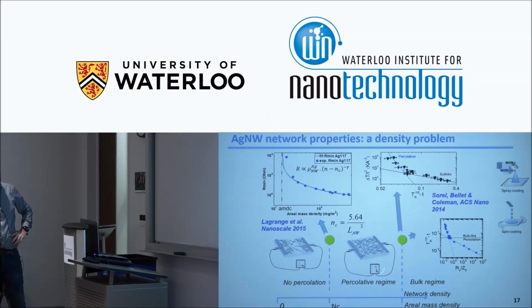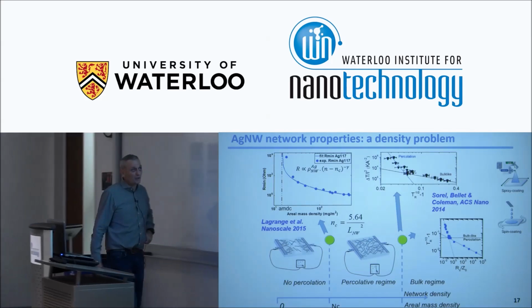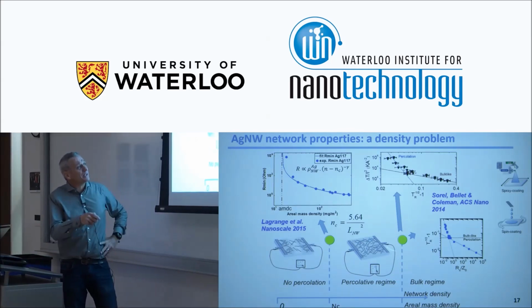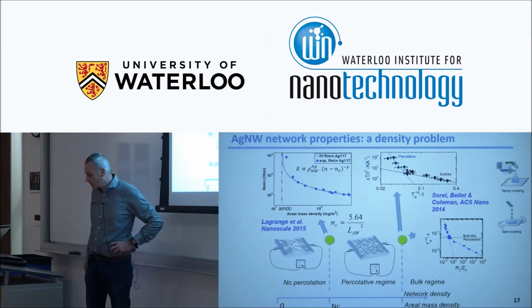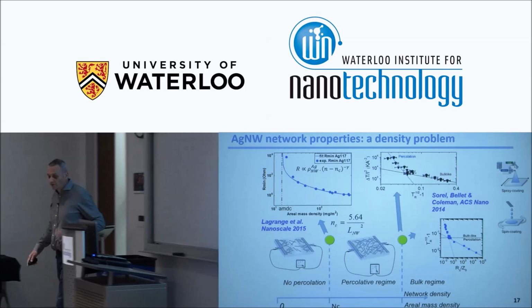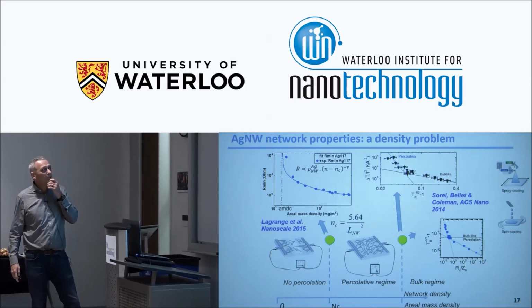There's another transition between the percolative regime and above. This is what we call the bulk regime, which is much better known and understood, but we can see that experimentally. For example, if we plot here in log-log scale the increase of temperature divided by the square of the intensity, thanks to the Joule effect, as a function of the transparency of the network, you can see there are two lines for the data in the percolative regime and the bulk regime. And the same if you plot the transparency versus the sheet resistance as well. In log-log scale, you can see as well the transition between the percolative and the bulk regime. So this transition is less understood compared to the stick percolation. But we can still observe that experimentally as well.